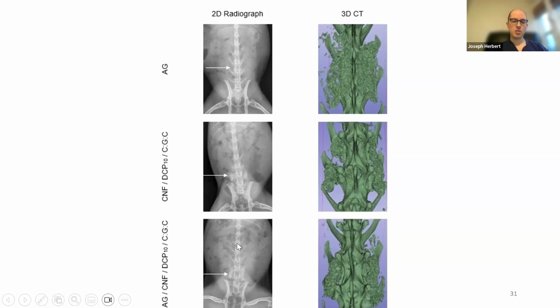But looking at these two rabbits here, this is the chitosan hydrogel by itself, and this is the allograft plus chitosan hydrogel. You can clearly see on these X-rays bone formation on these transverse processes and spanning these transverse processes. In particular, this is a particularly compelling picture of a bony bridge between these transverse processes, and that's the allograft plus hydrogel group.